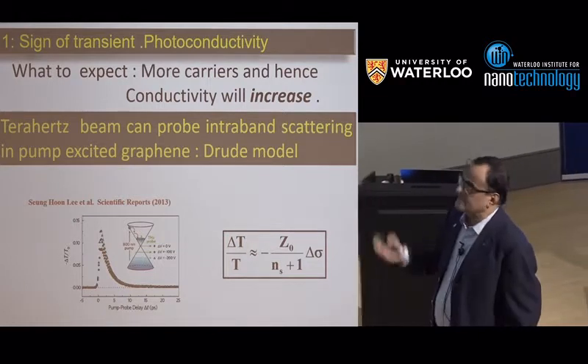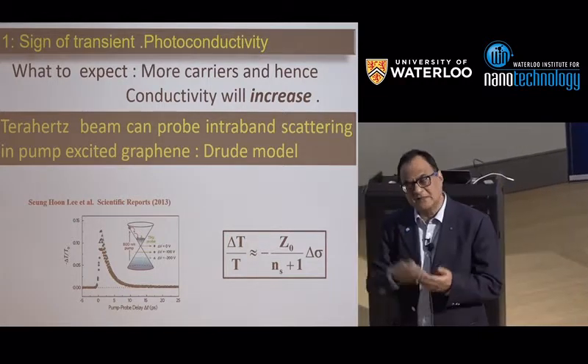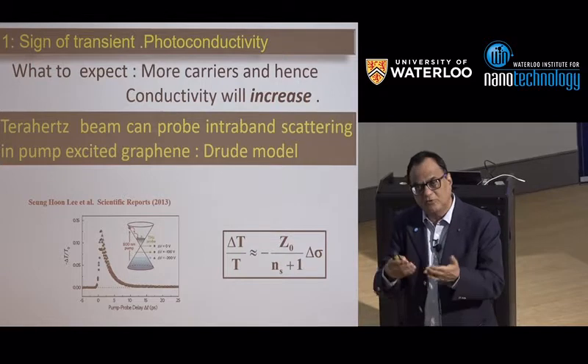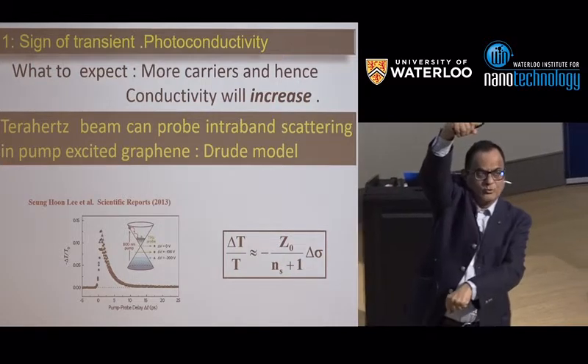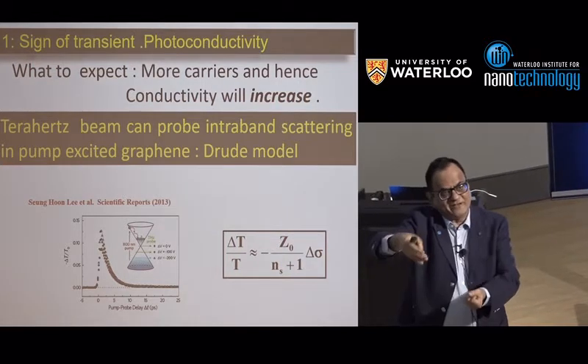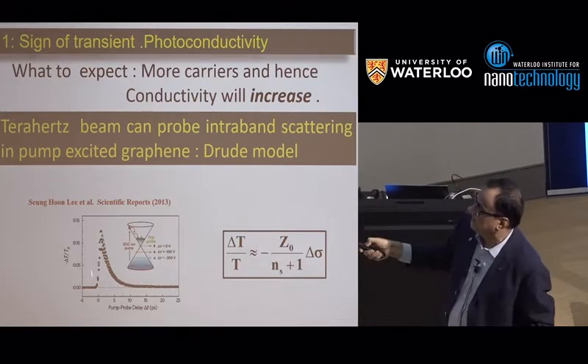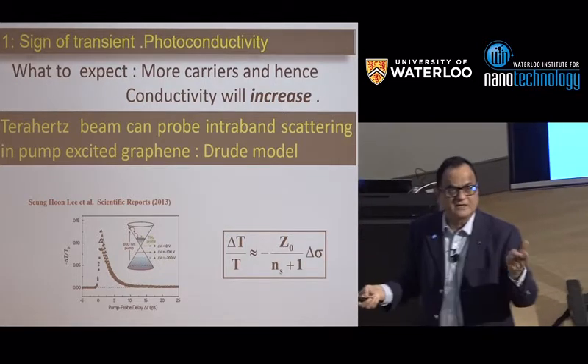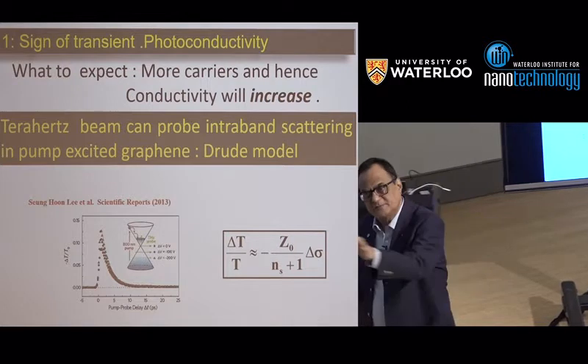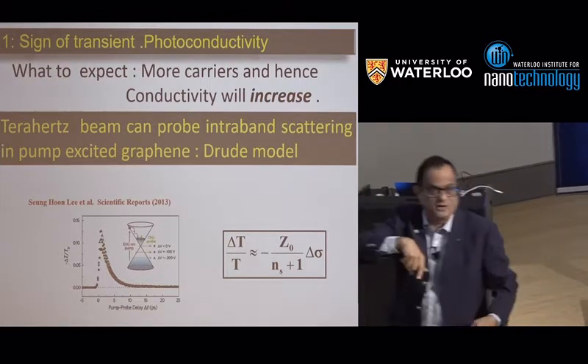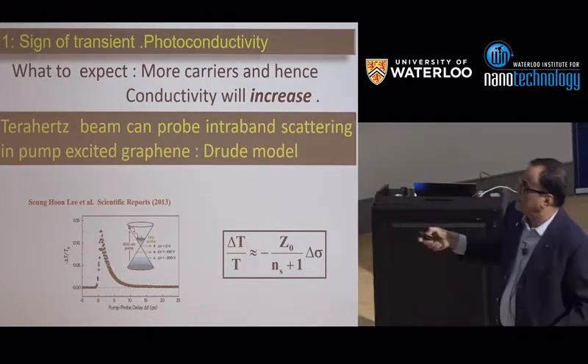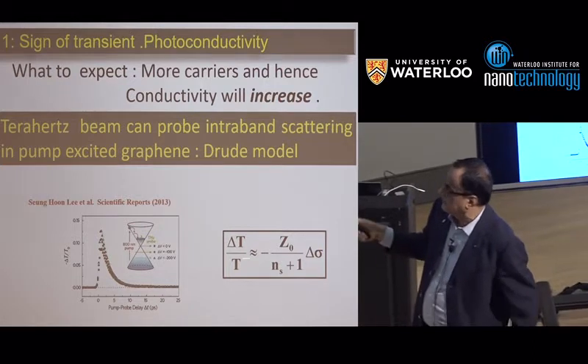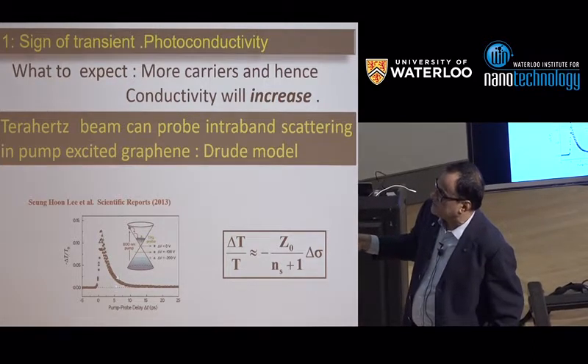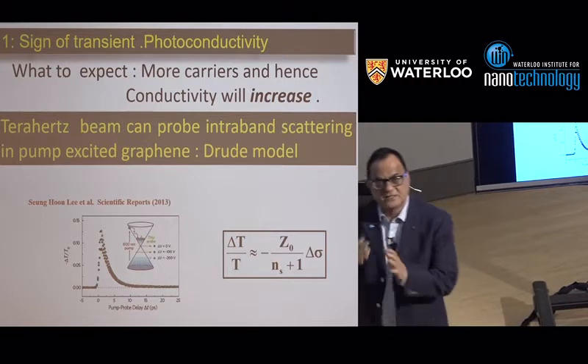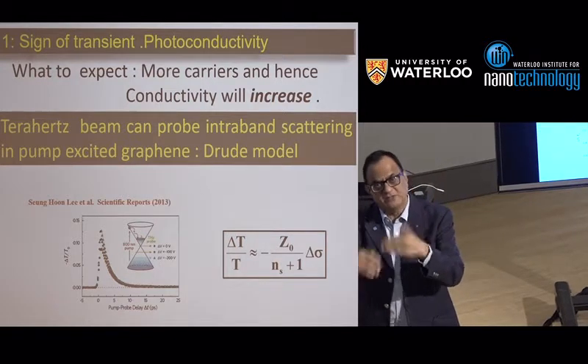And what do you expect? What we expect is that pump photons will make electron-hole pairs, increase the conductivity of graphene. You measure that by the transmission route. You measure the transmission of the graphene and convert it into conductivity. No brainer, and it just works, and the conductivity decays over 5 picosecond. So this is the relaxation time of carriers which we want to understand.